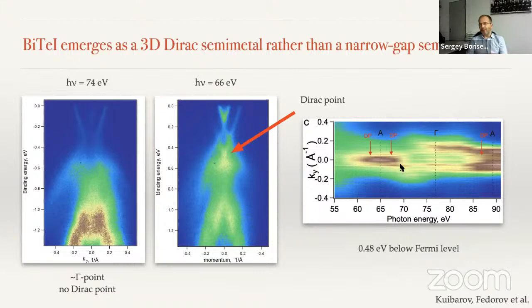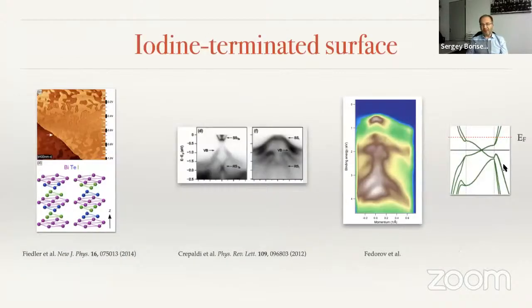So we interpret this as having two Dirac points here and here. Of course, we still have moderate KZ resolution, especially in this energy range. So this is all smeared out, but it's consistent with our interpretation, and these spectra represent the bulk dispersion. What does it mean to us? That, of course, having the Fermi level here and the Dirac point here, just doping the material by holes would be nice to have a great material, but of course it's very difficult.